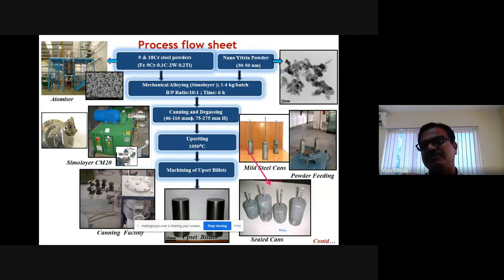So that's why these materials are to be hot worked. So in this case, how do we hot work it? We do the hot extrusion process. When you are hot working it, you cannot expose this material to air at high temperature because it gets oxidized. So that's why the powders are filled in cans. These are the cans, filled with a pneumatic vibrator so that you get a good tap density. Then the cans are connected to a vacuum degassing facility, which is heated at around 400 to 450 degrees centigrade, where the absorbed gases on the surface of the powder particles come out, and then the cans are sealed under vacuum.